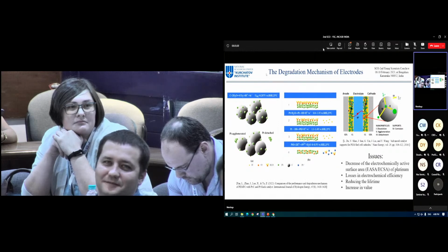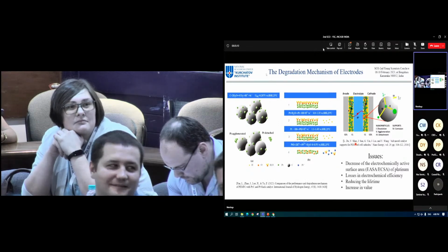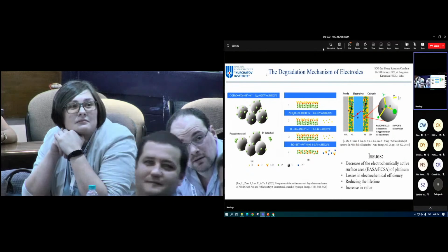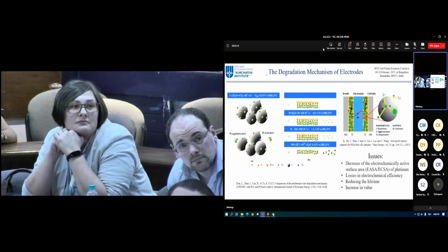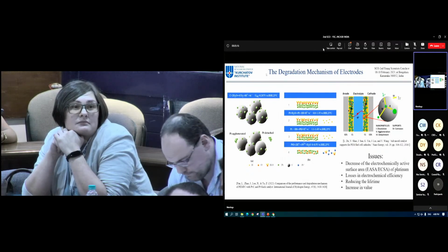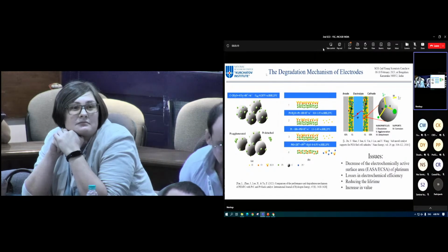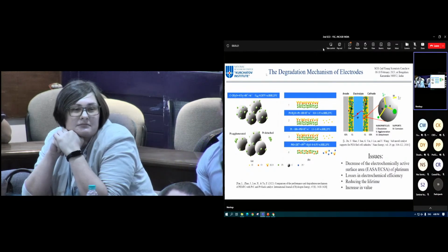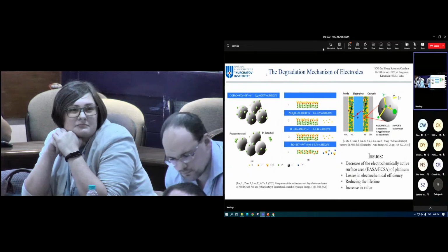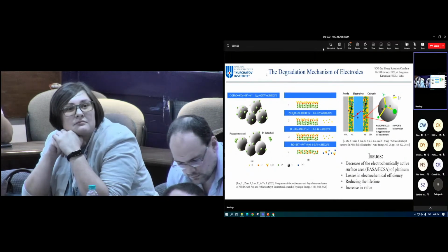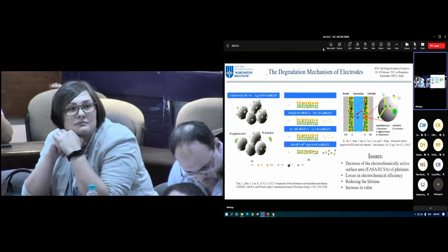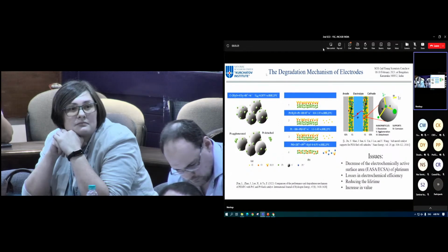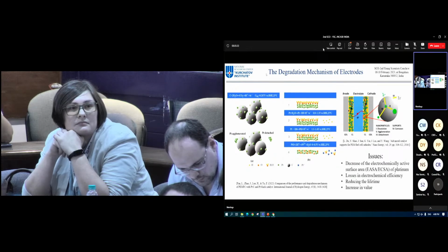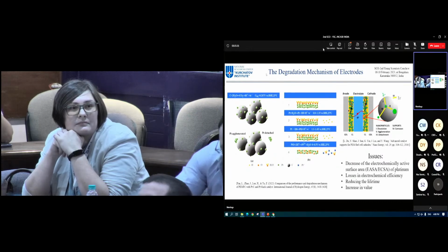The dissolution of platinum, the particle enlargement, and the carbon-support corrosion are the main reasons causing a loss of activity and a decrease of the catalytic electrochemical active surface area. A decrease in the platinum content and an increase in the activity and durability of electrocatalysts are important for the commercialization and widespread introduction of fuel cells.